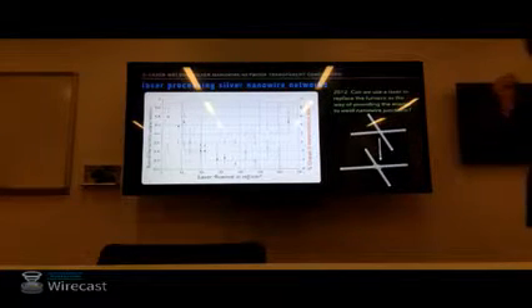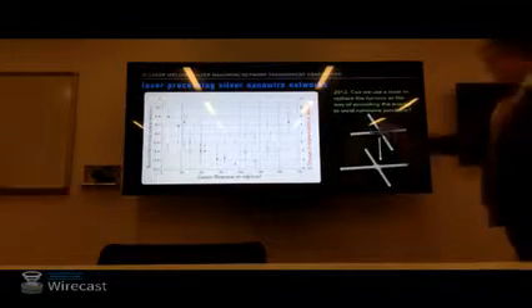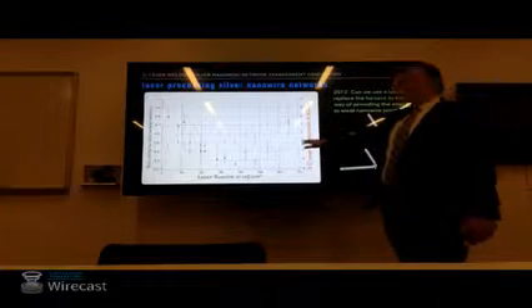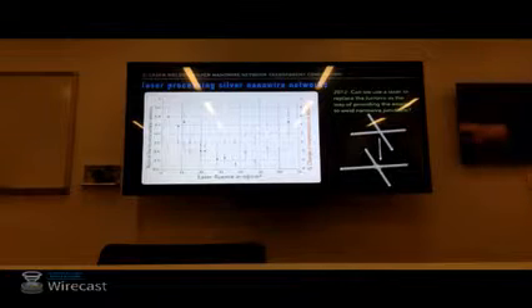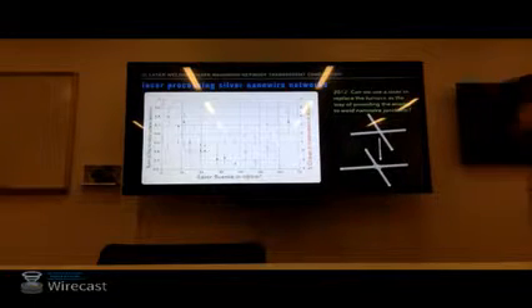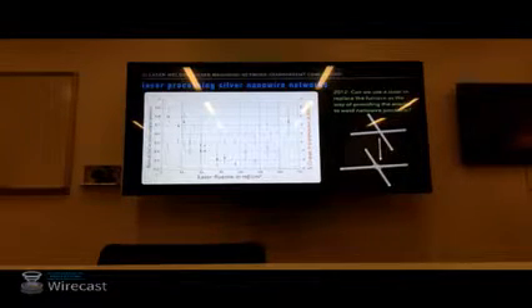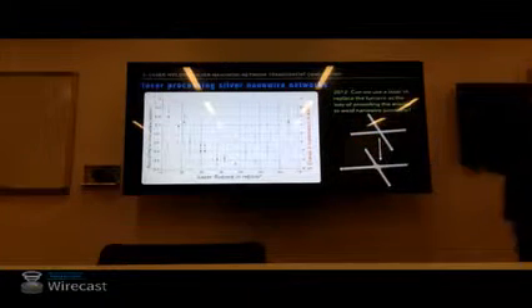For good measure, we can also track the optical transmission of these devices. We don't expect to see a change from the laser processing. And what we see is exactly that. So our 0 line for the red data here, no change to optical transmission within the error bars until we get to very high laser fluences. What we're doing there is removing material with the laser. We're ablating with the laser, and we don't want to do that either. So really this describes, say, 20 to 40 millijoules per centimeter squared optimal processing.